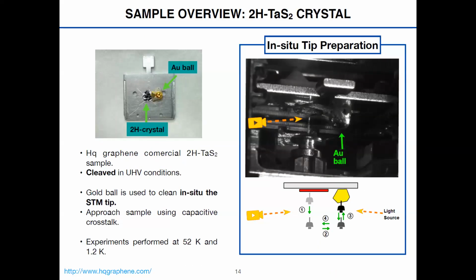This is the sample we studied. It's a commercial 2H tantalum disulfide crystal. We cleave it in UHV, and it's adhered to the sample holder with a silver epoxy. We also adhere close to it a gold ball that we use to prepare in situ our STM tip. So with the shields closed, because we have another optic port, we can prepare our sample without opening the thermal shields and therefore contaminating it.